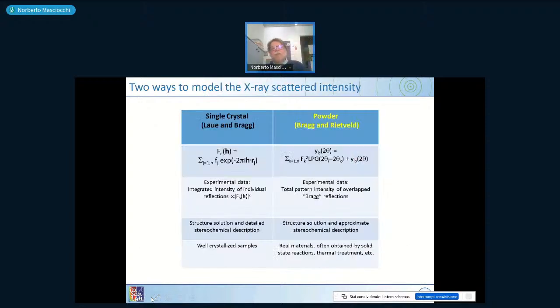So what we have seen now, in the first slide, we have seen Laue and Bragg. They developed a theory for single crystal data based on this function you see there. This is a structure factor function. It's possible to use well-crystallized samples, and you get as an output a structure solution and a detailed stereochemical description. These techniques were soon adopted in the late 1960s or 1970s by Rietveld, who used the Bragg theory and adapted it to a different formulation, where the experimental data are no longer the integrated intensity of individual reflections, but the total pattern intensity of overlapping Bragg reflections. So this is adapted for powders, from single crystal you go to powders.